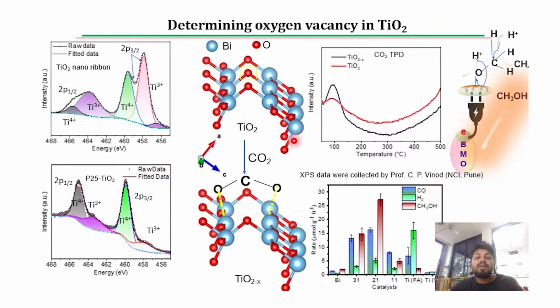In the next chapter, we have activated TiO2 in visible light, where we have mainly exposed titanium 3+, which provides more active sites to bind the CO2 in the oxygen vacancy, and therefore we found improved CO2 adsorption, and thereby we got better results. And in the composite 2,1, we got methanol as a major product. Here you can see upon the protonation in this oxygen center, we got methanol as a major product.